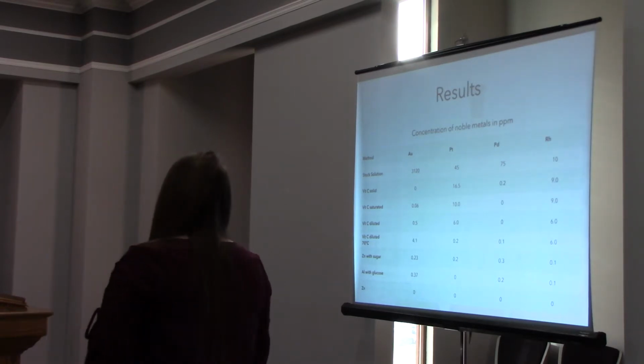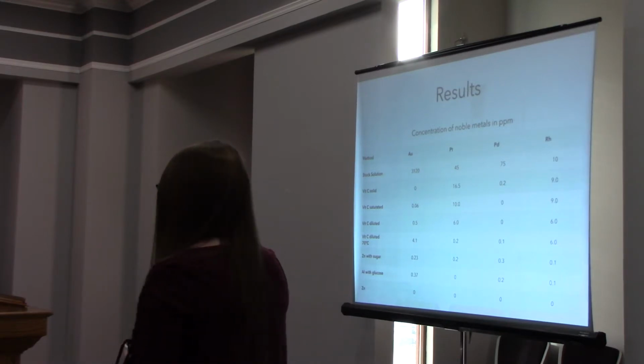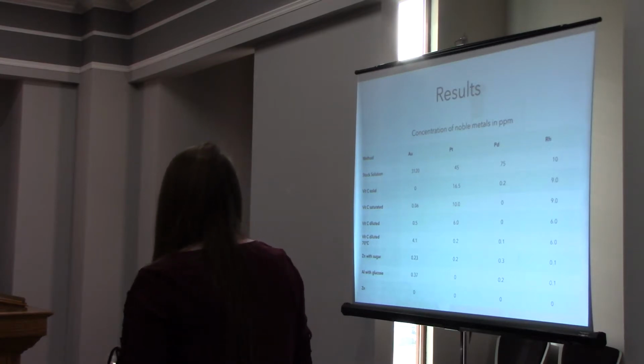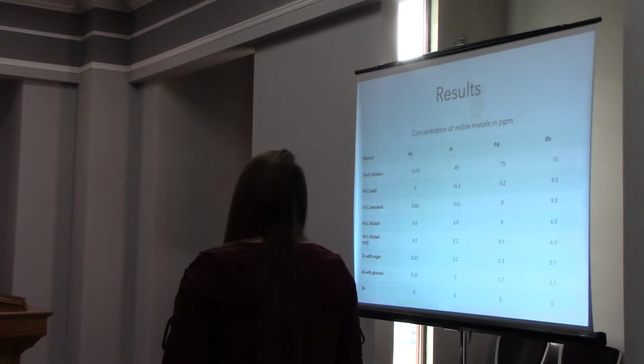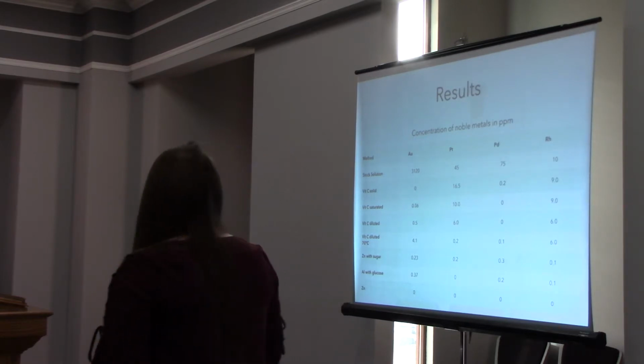So the results. Why do we care about all of this? The stock solution had these numbers of ppms of the gold, platinum, palladium, and rhodium in it. And the 2 methods, vitamin C, and zinc and aluminum, had different results for how much they pulled out of the solution. The vitamin C pulled out pretty much all the gold, and then pretty much all the palladium, and then it pulled out platinum when it was heated up.